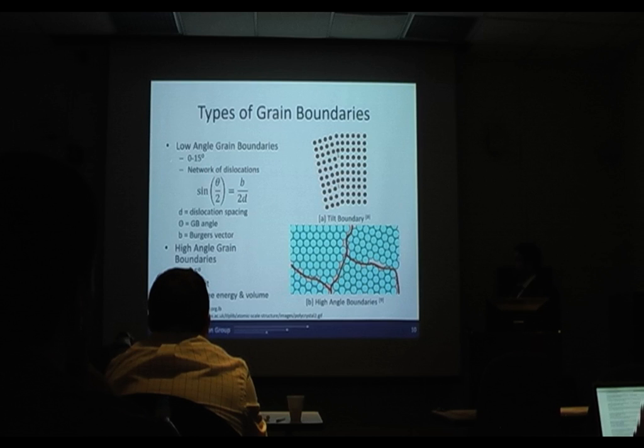If you have a larger than 15 degree misorientation, you have what's termed a high angle grain boundary, and there you typically have a much poorer fit, and that's shown in the bottom image. It doesn't line up as nicely as it does in the top. And this causes much more free volume and free energy, which can be seen as the white space.